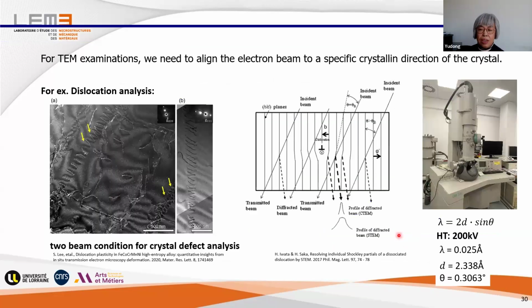And so you see, for TEM operation, we always need to specifically align the beam with respect to a specific crystalline direction to have a desired contrast. For example, to analyze dislocations, to visualize a dislocation, we have to position the beam, allowing this beam in Bragg condition, more or less, with respect to here is the dislocation, and with the plane here.